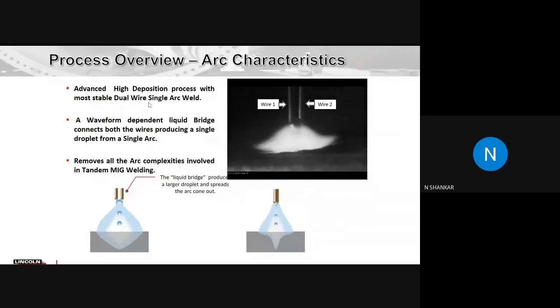It's an advanced high deposition process with a stable, dual wire, single arc weld. It's waveform dependent. You see a liquid bridge will connect both the wires and it will allow you to deposit one single weld puddle, one single arc and one single droplet, but it will give a wider cone with a deeper penetration and takes care of good weld quality actually.